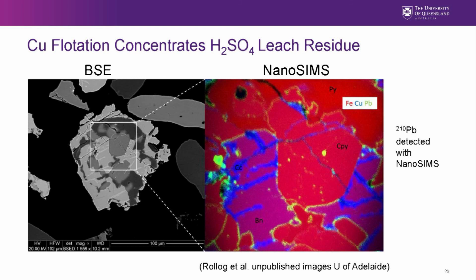But lead is green, and you can see that the lead, and this is lead 210, is actually very concentrated on the grain boundaries and on the surfaces, maybe not shown in this particular image. So this is some direct evidence of the location of these radionuclides. They're sitting at the ppb level, so we think that this lead 210 here might be, in the sample, on the order of less than 5 ppb. The detection limits are not, this is an emerging characterization technique, and so hopefully there'll be some information coming out about that. But it's very interesting to be able to resolve where the RN elements are, even though they're at the ppb level.